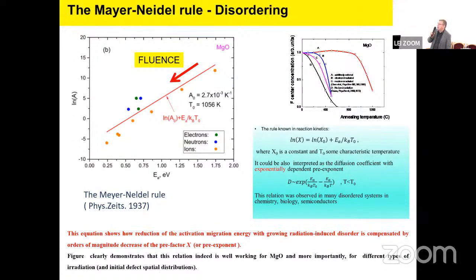So we collect all data, what we found in literature, and we analyze this data, also our data, which we obtained in our crystals, in Darmstadt, in Kazakhstan, Dubna, and Helsinki. And we found firstly that activation energy of defect annealing is different in all cases.